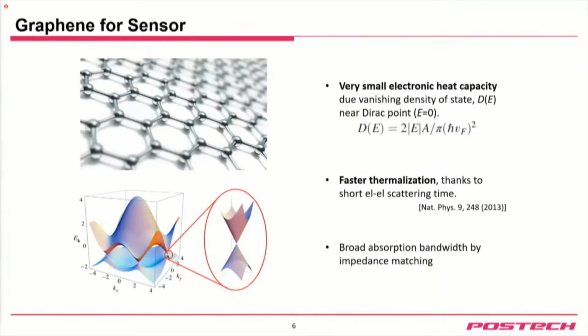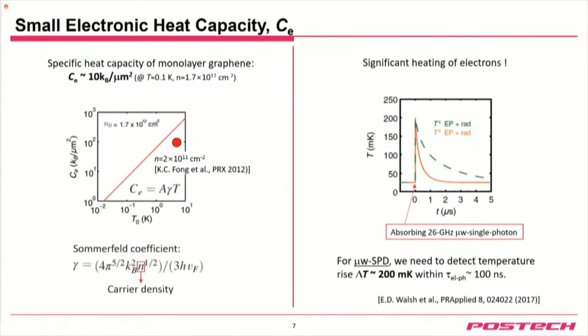That's why we use graphene as an absorber. Because graphene has a linear band structure, when the Fermi level is at the Dirac point, the electronic density of states basically vanishes. So the electronic heat capacity also almost vanishes, and we may be able to have very high sensitivity against energy perturbation. In fact, Dr. Fong in 2012 already measured the heat capacity of monolayer graphene, and it was almost 10 times the Boltzmann constant per square micrometer, which is very comparable to the fundamental unit. This is very small. And the estimated temperature change when a 26 gigahertz microwave single photon comes into 1 by 1 square micrometer of graphene is about 100 to 200 millikelvin change in electron temperature.